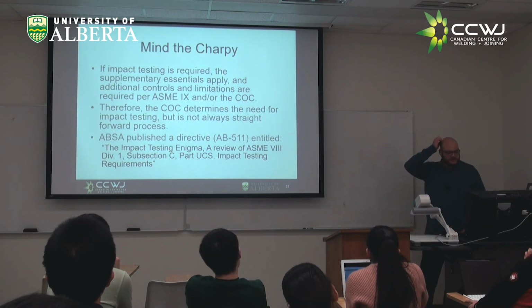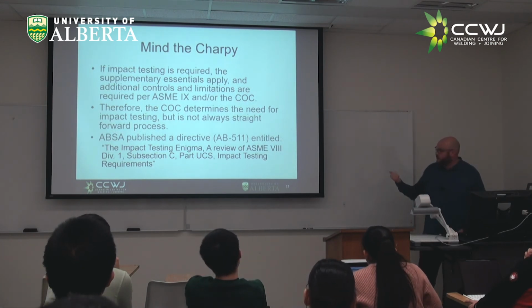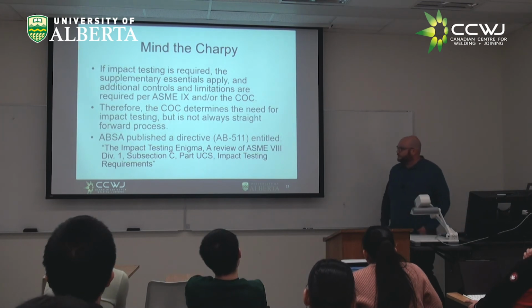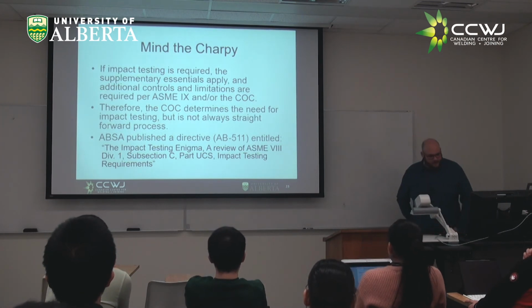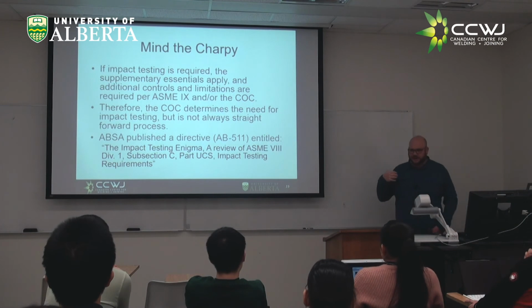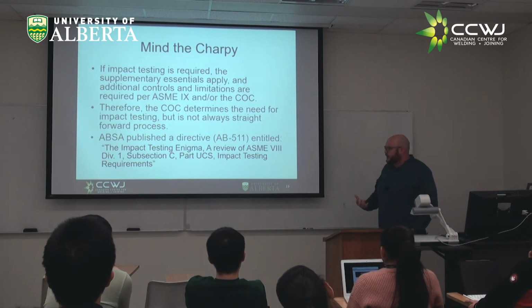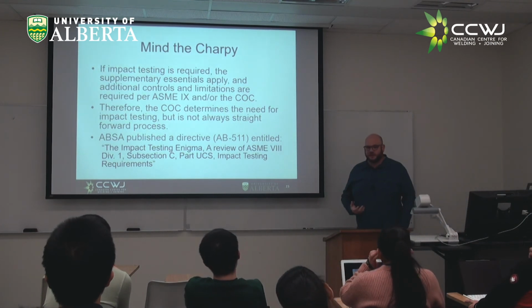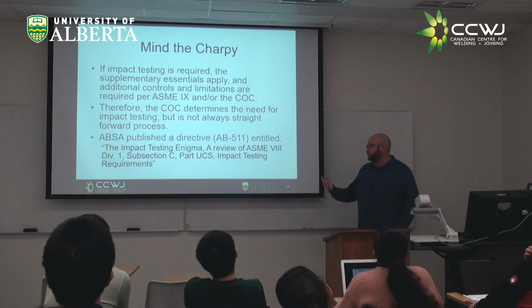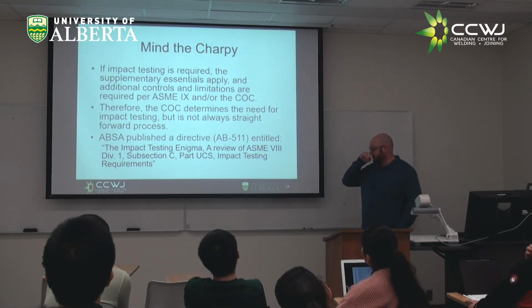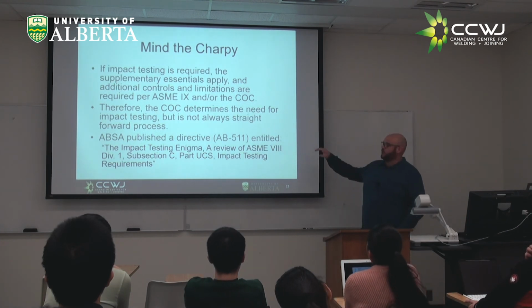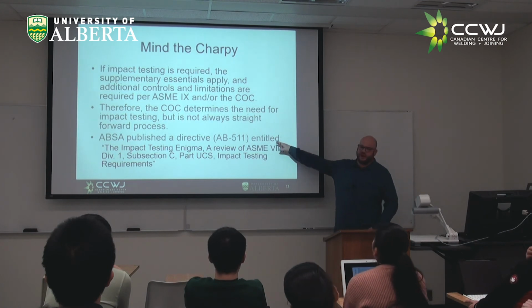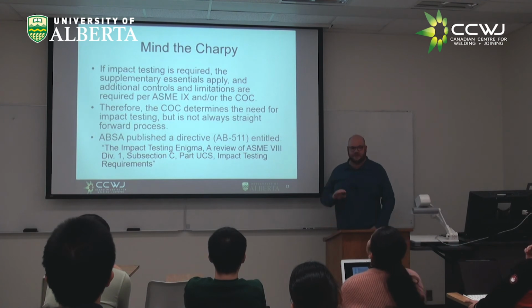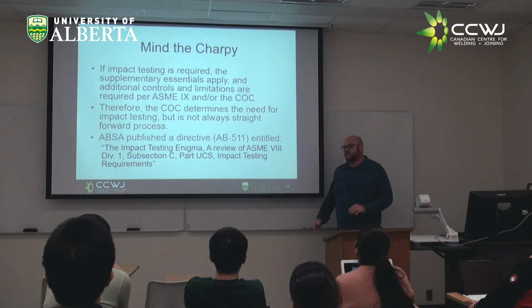So you have to understand how the code of construction approaches it, and then also ASME 9. The problem is the code of construction, which drives this whole thing, is not usually straightforward. For example, ASME 8 Div 1 for pressure vessels in non-cyclic service is so horribly complicated that ABSA took the time to publish a directive that's like 24 pages long, which is basically summed up by: Charpy testing is complicated, but it's also really important.